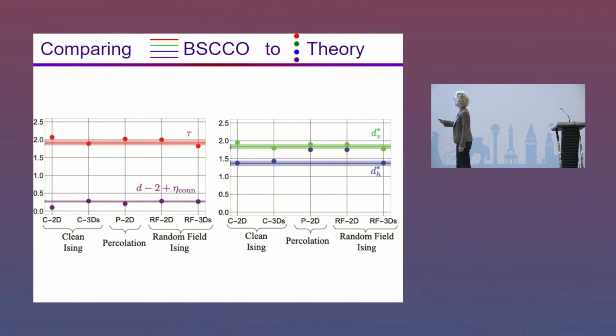The left two columns are about the clean Ising model, whether 2 dimensions or 3 dimensions. The middle column is about percolation physics, so this would be just non-interacting. Because it's non-interacting, you only consider the 2-dimensional case because the observation of the STM is on a surface. And in the last two columns, we have the random field Ising models, whether 2 dimensions or 3 dimensions. And you can see, for example, that as is the usual case, critical exponents are sensitive to dimension. Here as well, in the clean Ising model, this critical exponent is sensitive to dimension.